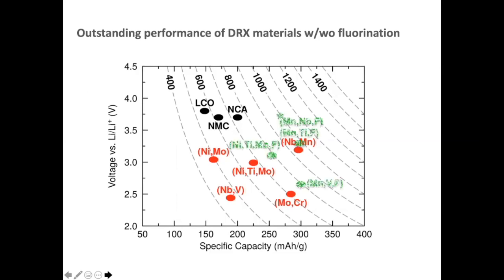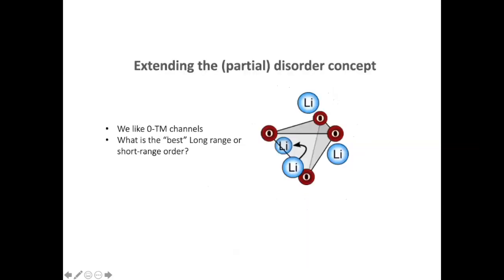So these DRX materials have outstanding energy numbers. The red here is the oxides on a specific capacity versus average voltage plot. The green are the oxyfluorides. And again, from the abundance perspective, you see a lot of materials here with manganese, which would be a much more earth abundant material to make cathodes with than some of the things we use now.